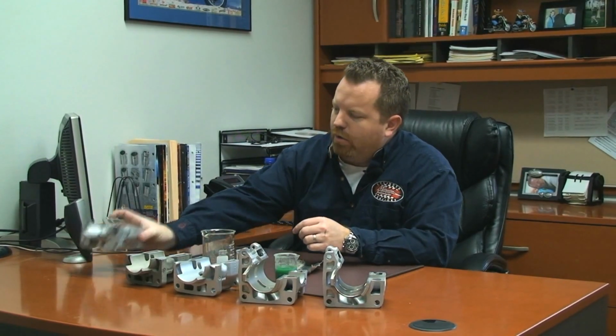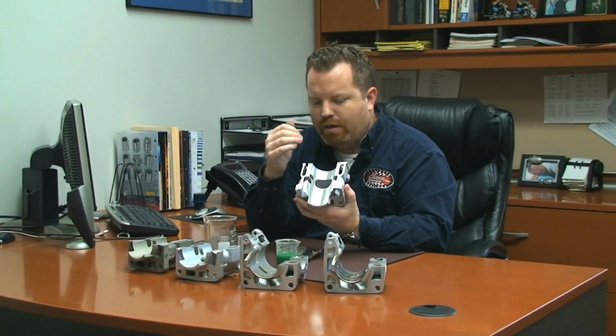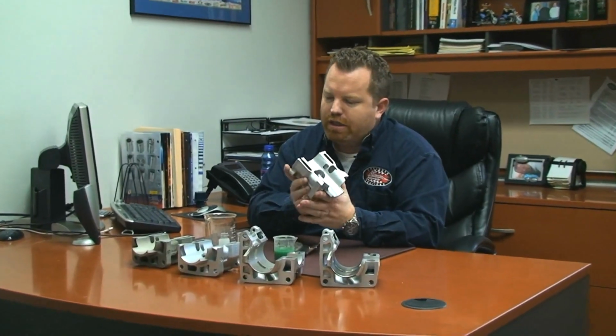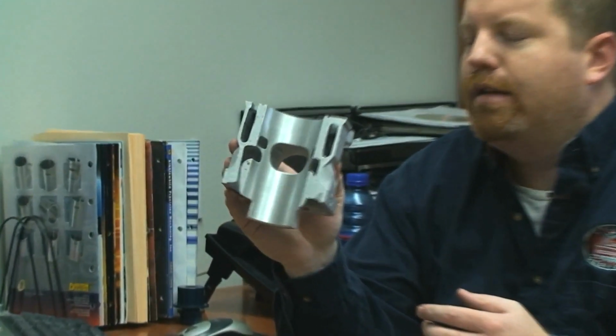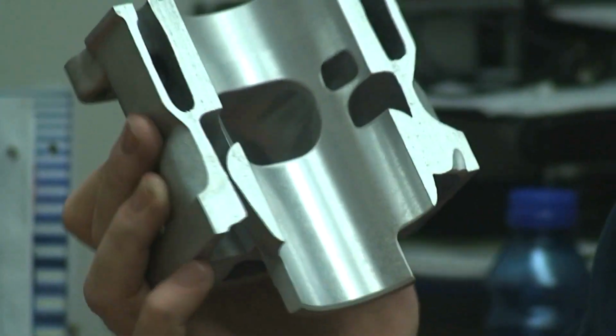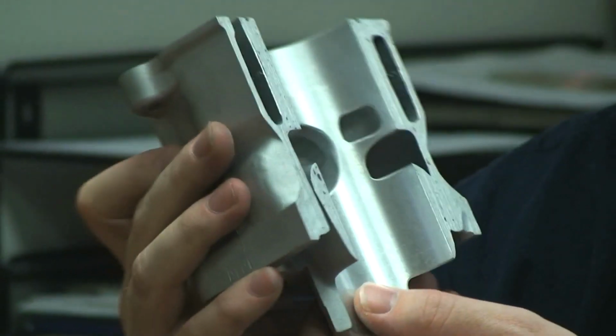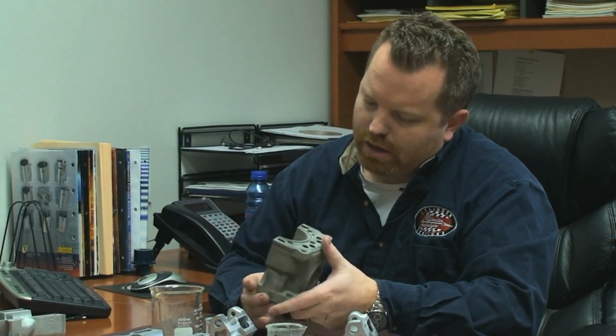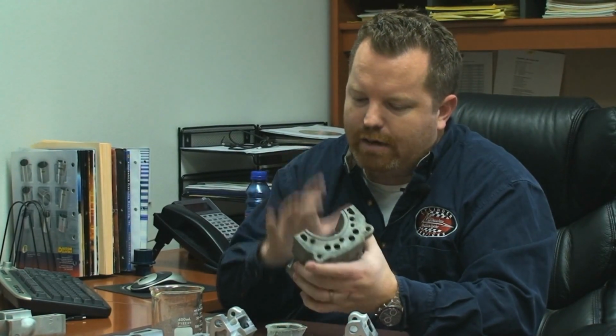Once we get the weld in the bore, we have to go in and do a light cut on the bore and clean everything up, and sometimes we just have to do this light cut. So this is what the cylinder looks like right before it goes in the plating tank. The bore is nice and smooth and clean, and it's ready for plating. Once it is sized, we know how much plating we need to put on. It goes in a plating tank, and there's an electrical charge put to an anode that's down in the center of the bore, and that current will carry the material that's in the plating bath onto the wall of the cylinder,